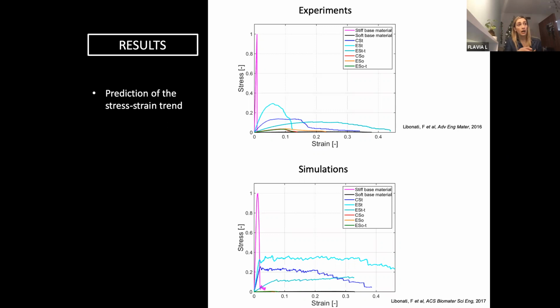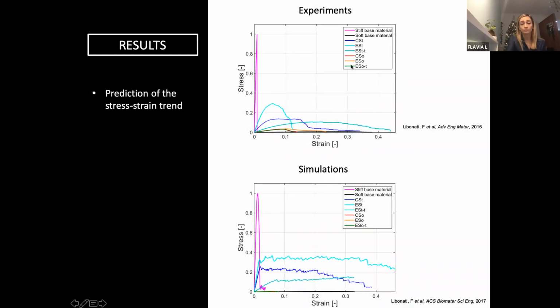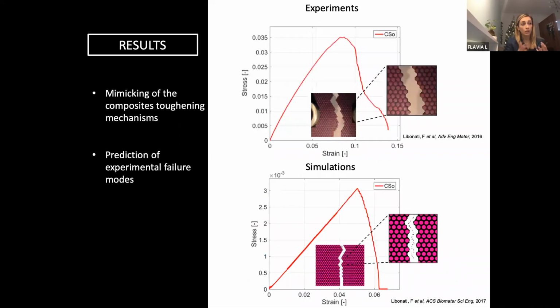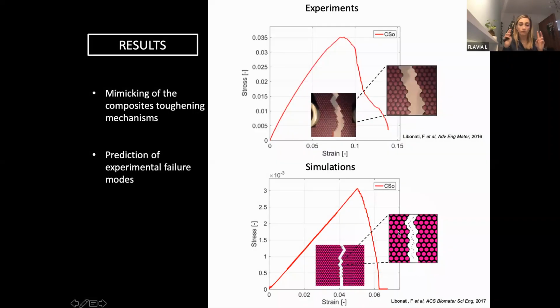You can see how we can get the stress strain curve for homogeneous material, but also for all the topologies. And if we do a one-to-one comparison, we can see how we can mimic the stress strain curve. But what is really interesting is that we can really get an insight into the material behavior and see how the crack propagates in each topology.